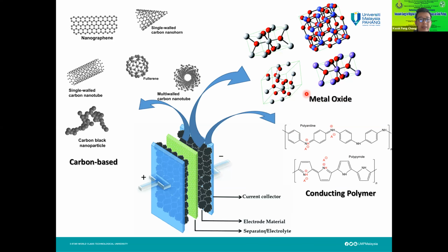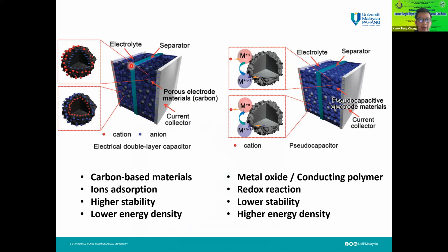And for the comparison between both, we look at this: we have the current collector, then the electrode material, and then the separator. If we look at the carbon-based material, such as graphene, carbon nanotube, or fullerene, the energy storage principle in this supercapacitor is based on ion absorption. So it depends on how the ion can absorb onto this carbon material. The advantage is that it has a very high stability, because you are not going to change the oxidation state of the material. So that's why you can keep on using it for a very long cycle. But the drawback is that there is a limitation on the energy density.